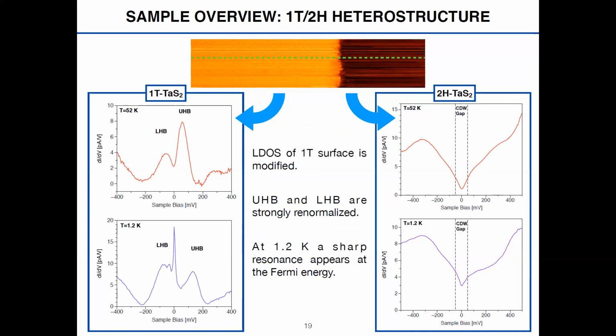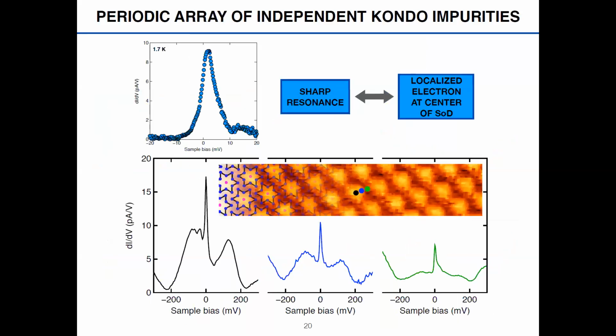However, when you go to the 1T phase, so in this area here, what you see first of all is that your lower and upper Hubbard bands appear at different energy positions. So they are renormalized because now you have a metal below. And when you go down to 1.2 Kelvin, this strong zero bias resonance appears at 0 voltage that we believe is a Kondo resonance. And it's what I'm going to try and demonstrate in the following slides.